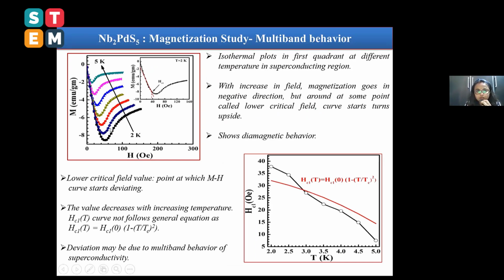And this is the isothermal plot in the first quadrant. Here you can see with increasing field, magnetization goes in the negative direction, and at some point it starts turning upward, and that is the lower critical field. This is the lower critical field versus temperature plot, and it is not fitted using the general equation, which may be due to the multiband behavior of superconductivity in this case.